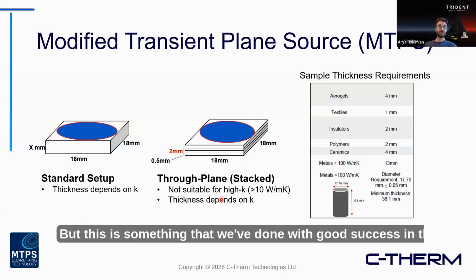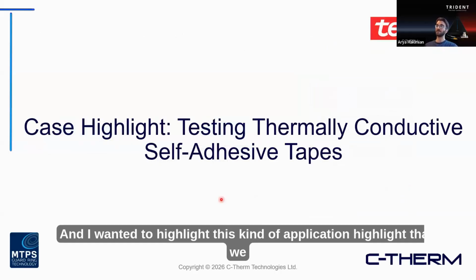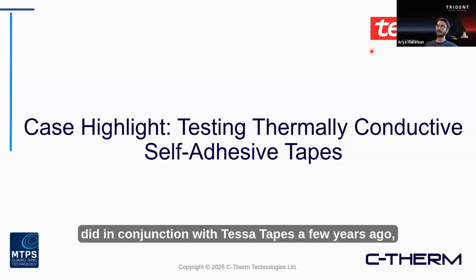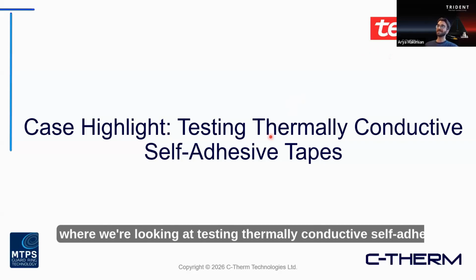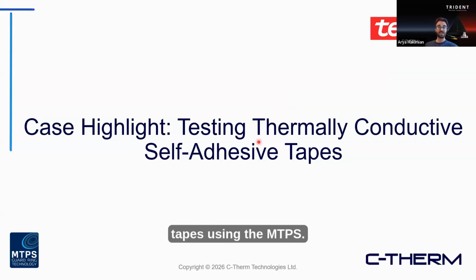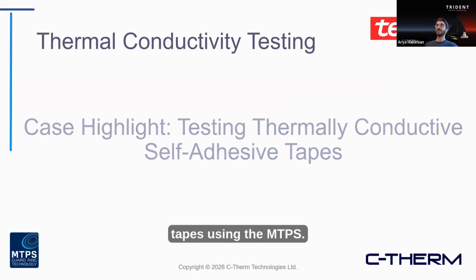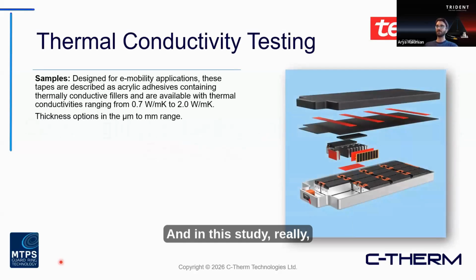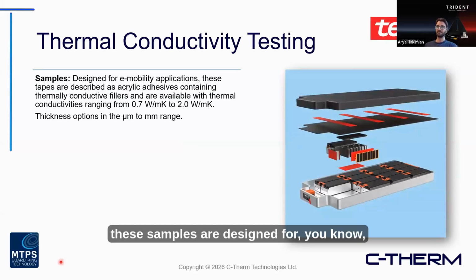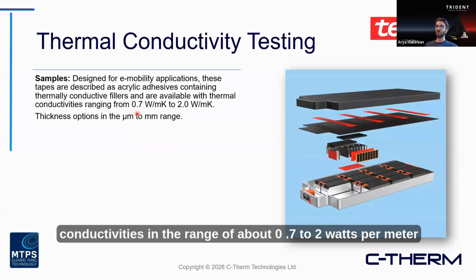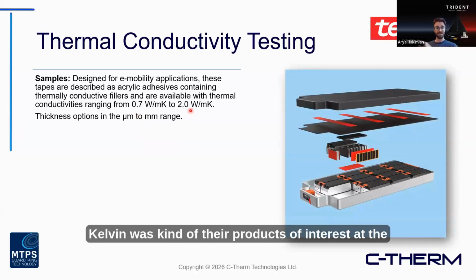But this is something that we've done with good success in the past, and I wanted to highlight this application that we did in conjunction with Tesa Tapes a few years ago, where we were testing thermally conductive self-adhesive tapes using the MTPS. In this study, these samples are designed for e-mobility applications. Thermal conductivities in the range of about 0.7 to 2 watts per meter Kelvin were their products of interest at the time.